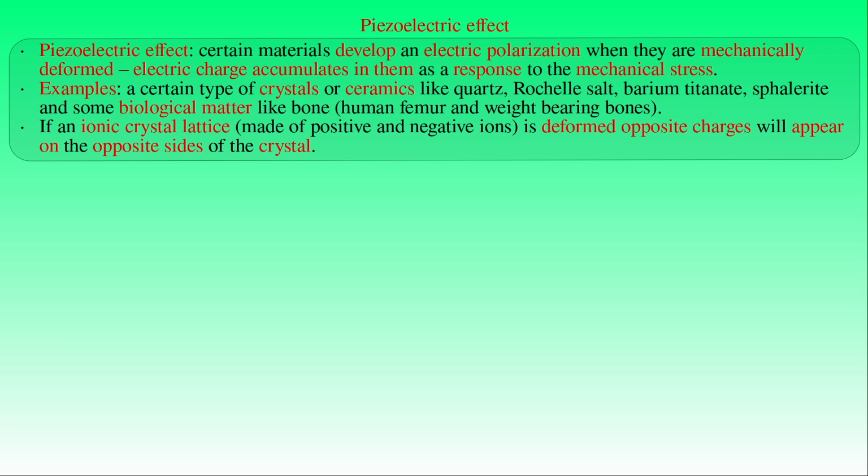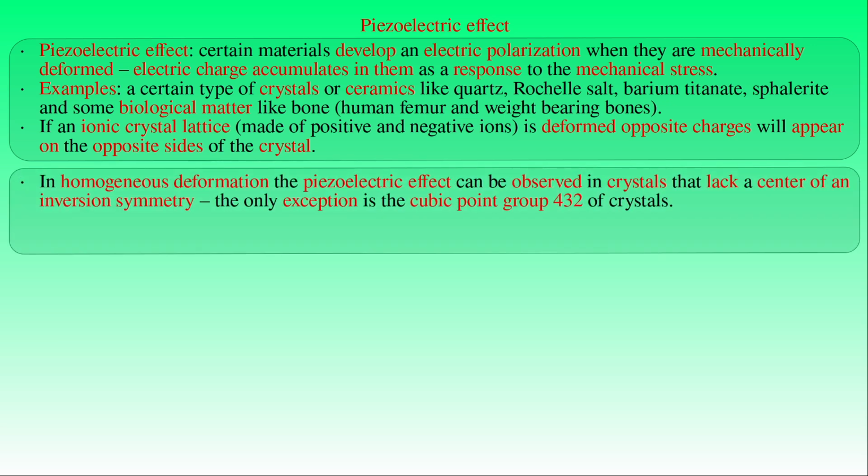The most controlled way to produce mechanical stresses in a crystal is a homogeneous or uniform deformation, where mechanical stress or strain is applied uniformly across the entire crystal structure. Under uniform stress, the electrical response depends entirely on the intrinsic symmetry of the crystal lattice. In the case of homogeneous deformation, the piezoelectric effect can be observed in crystals that lack a center of inversion symmetry. The only exception is the cubic point group 432 of crystals, which is non-centrosymmetric but not piezoelectric due to its high rotational symmetry.